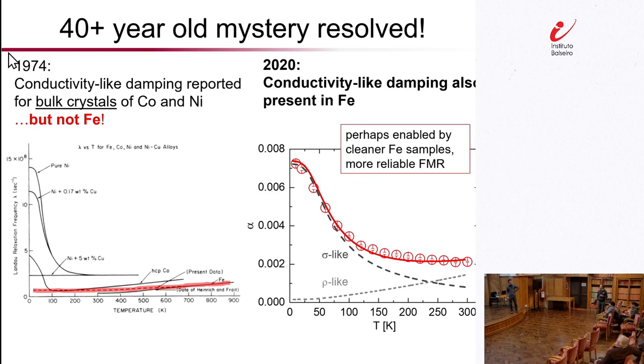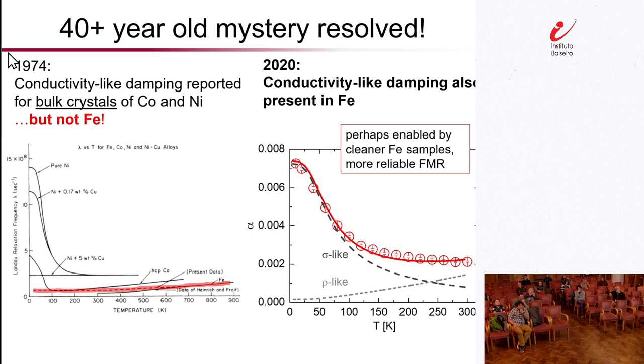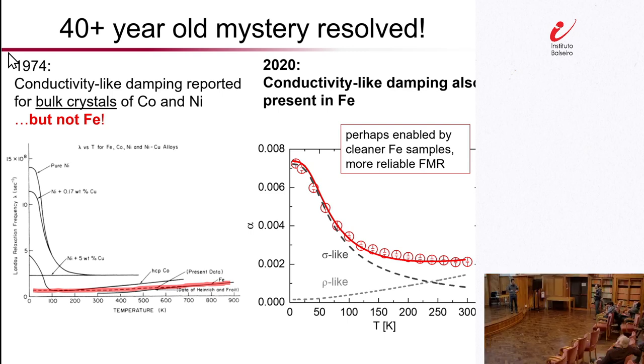So it could be any of those. On one hand, it could be defects in the lattice structure. It can be things like dislocations, vacancies, grain boundaries. It could also be impurities, where we have other kinds of chemical elements in there. And for films that are thin enough, I would imagine the surfaces would also play a big role, surface scattering.